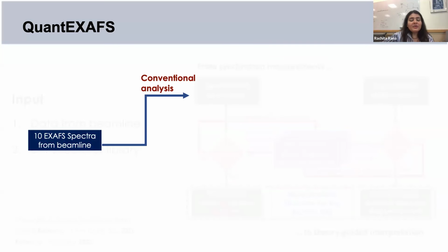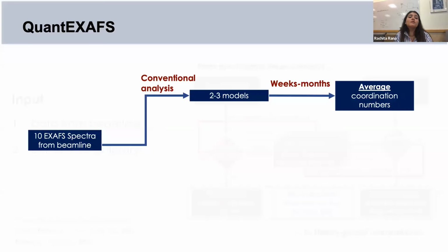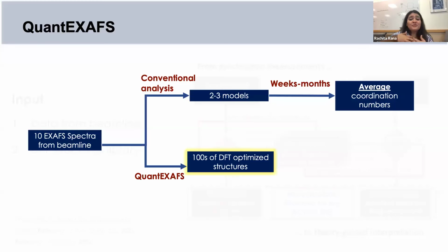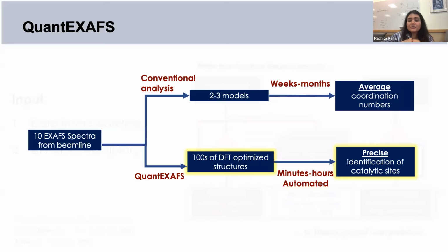So to simplify this, when it comes to the ease of using something like QuantEXAFS, if you have, say, 10 spectra from the beamline and you use conventional analysis tools, you're really limited by the number of models you would have if you're not using computational tools such as density functional theory. And then you also have to be very selective about the paths that you can use. And it takes you weeks and months to get that information about the average coordination environment of your material. And this works great if you have a very complex material. But if you have a well-defined system, nothing is stopping us from optimizing those structures, even if there are hundreds or 500s of structures. And then with QuantEXAFS, within minutes or hours in a completely automated fashion, you can get a precise identification of your catalytic site.